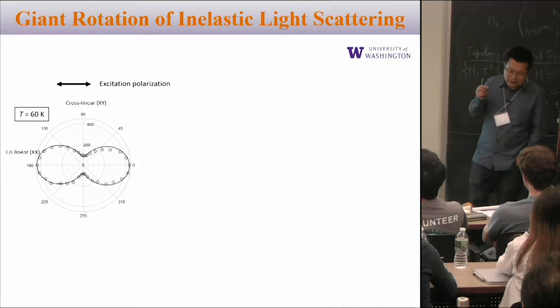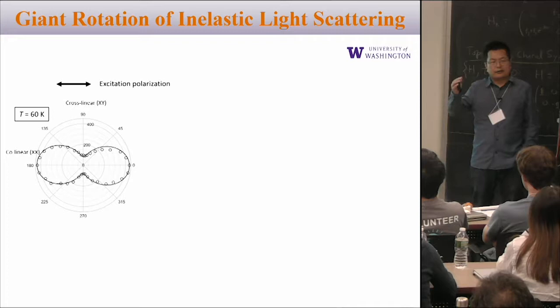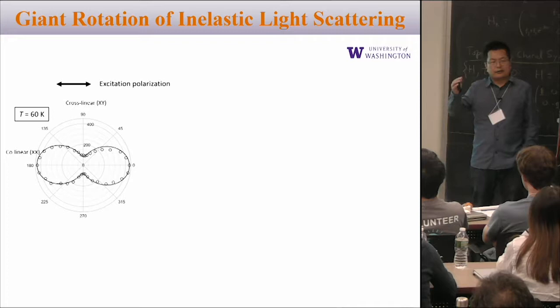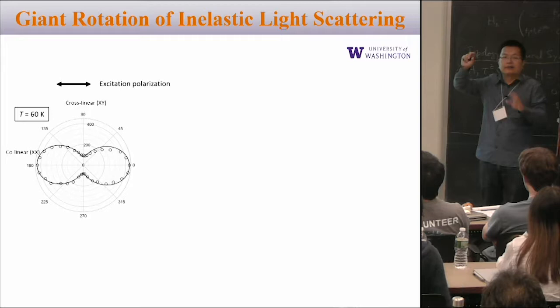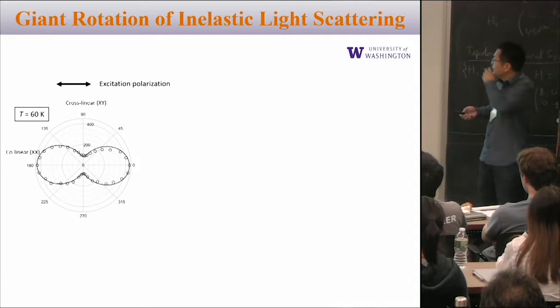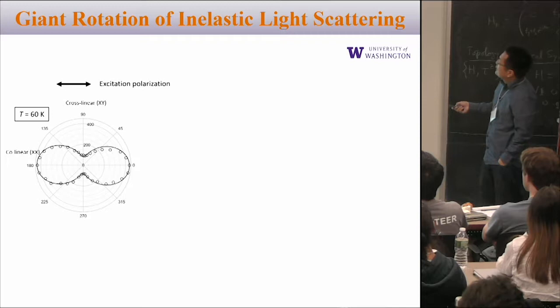What's interesting is that when we measure magnetic order, I always do Kerr rotation measurements — you shine linearly polarized light and look at the rotation angle at the same frequency. Now I'm going to show that we can also look at a similar Kerr rotation effect in the inelastic scattering regime, where the light comes out at a different frequency after interacting with the lattice — either emitting or absorbing a phonon. Let's look at the data at 60 Kelvin.